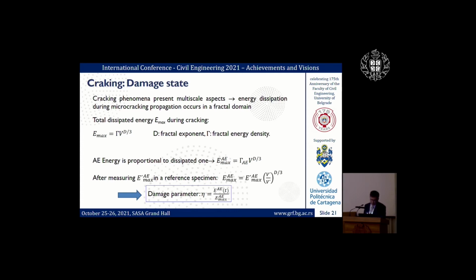Then you know what this total is, and use it as a damage parameter by measuring the total energy that you have measured at a certain time. So here you measure all the acoustic emission up to that time, divided by the total that you're going to have, and then you can use it as some kind of damage parameter to evaluate how your construction is.